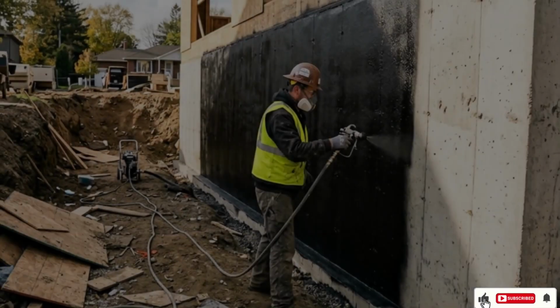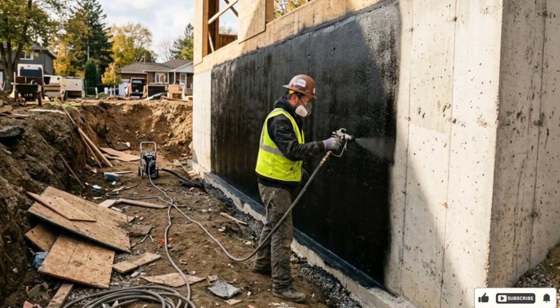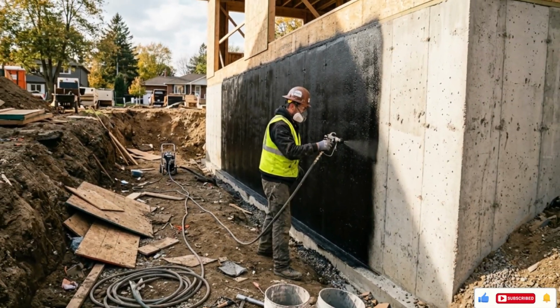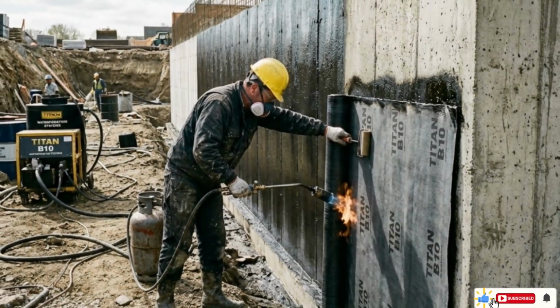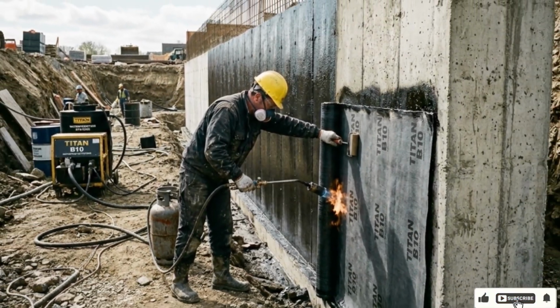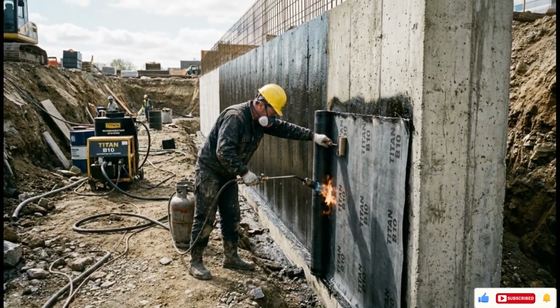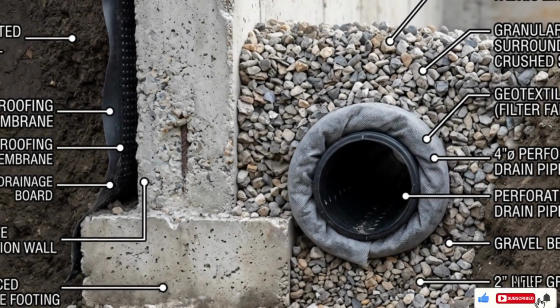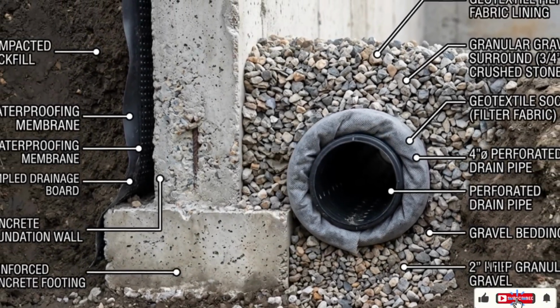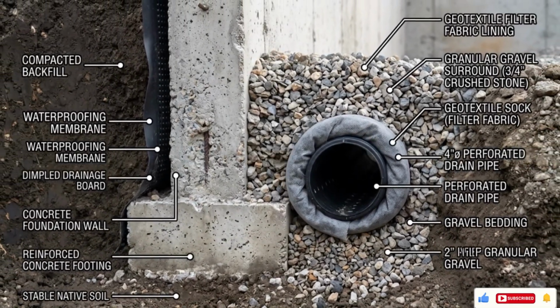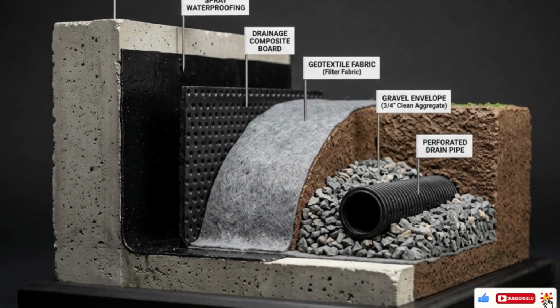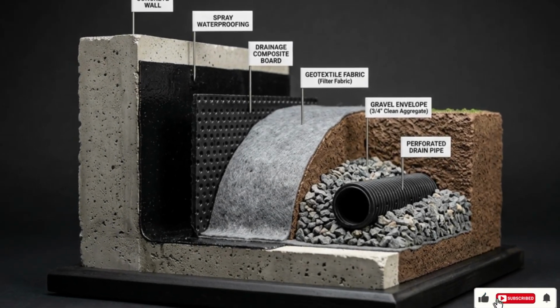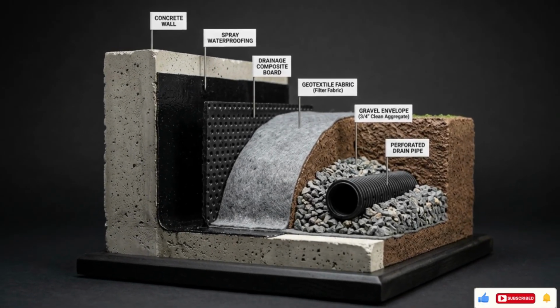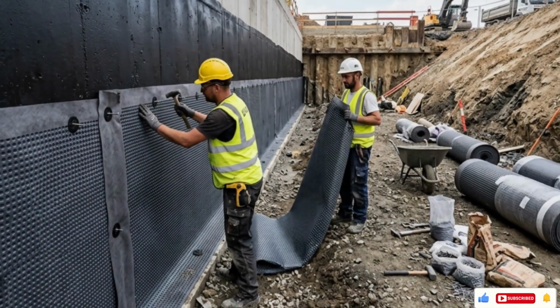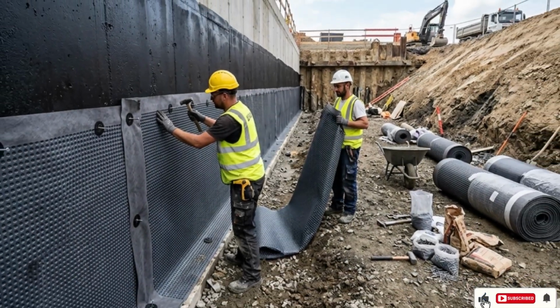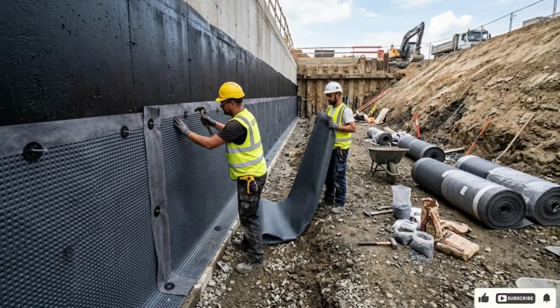Waterproofing systems. For below-grade walls, a spray-applied polyurethane or bituminous membrane on the exterior face, combined with a drainage composite board, geotextile filter fabric, and a perforated drain pipe at footing level discharging to a sump or gravity outlet. This complete below-grade waterproofing and drainage system adds $3,000 to $8,000 to a standard residential basement, but eliminates the most common cause of basement moisture problems. For slabs, the vapor barrier system described above, combined with proper perimeter drainage and site grading.